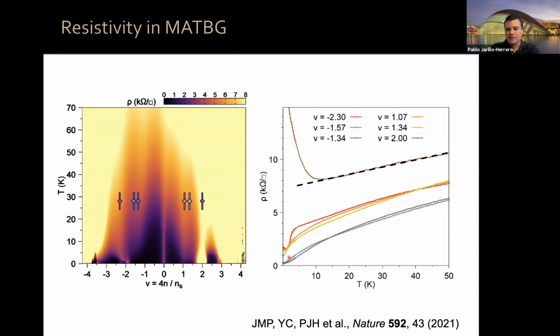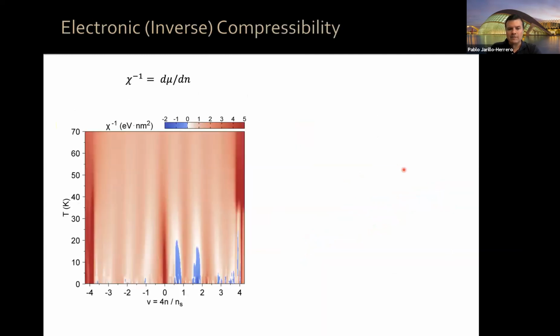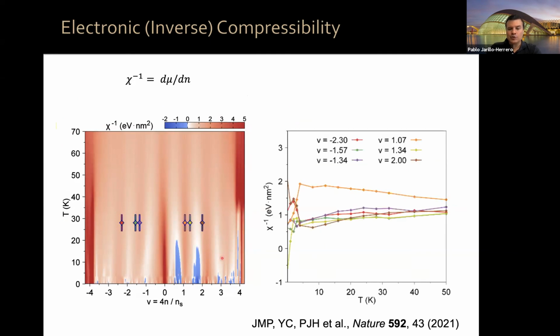I'm trying to avoid here the superconducting regions and also regions which exhibit negative compressibility, as I will show later. But you can see that it's linear or slightly sublinear behavior, very unlike what you expect from Fermi liquid behavior. Then we can measure the inverse compressibility by measuring the chemical potential as a function of density and its derivative, then as a function of temperature. There are some regions with negative compressibility, which are due to correlations. I'm showing you traces here trying to avoid that negative inverse compressibility, because that has nothing to do with strange metal behavior at higher temperatures.